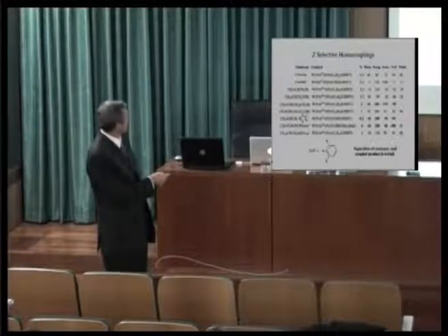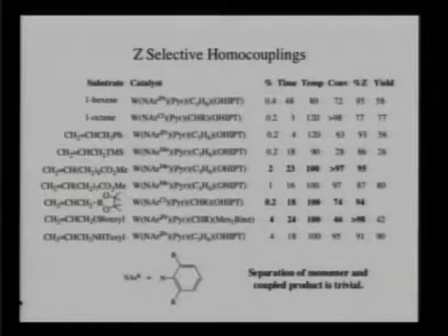But the yields can be high, and the percent Z of those yields quite high, greater than 98 in this case of this allyl benzyl ether. Only a 46% conversion, but a 98% Z product, virtually only Z. The yield is not such a big problem because you're making a product that weighs almost twice as much as what you start with, so it's easy to separate the product from the starting material.